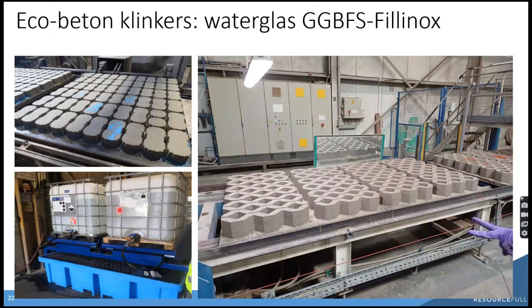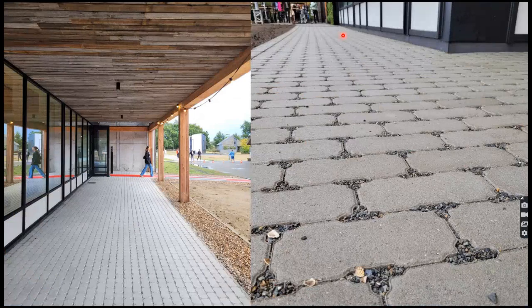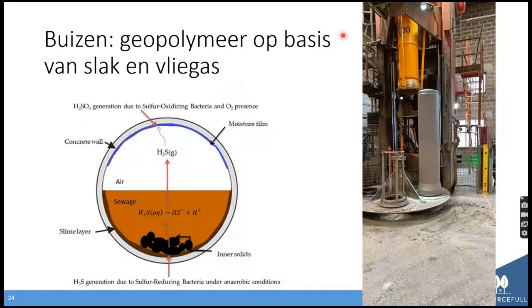You know, if you mix the slag with water, nothing happens. You need to bombard it a little bit with stronger chemicals to make it react. And here you see it was a mix of stainless steel slag and blast furnace slag, where we put 1,000 square meters of these pavers in a new building. We are making sewage pipes with a combination of slag and fly ash.